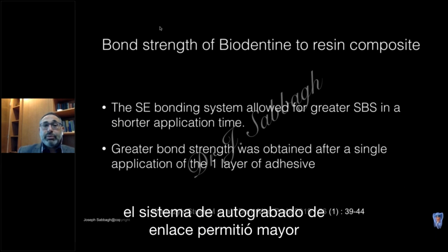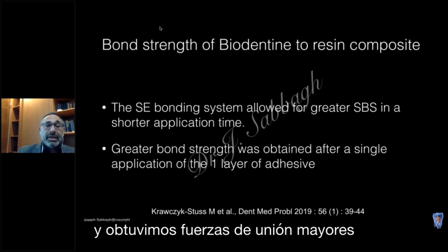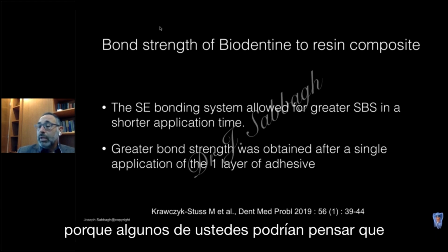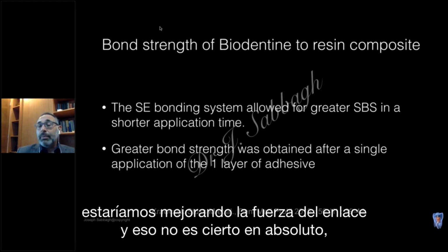The self-etch bonding system allowed for greater shear bond strength in a shorter application time, and we obtained greater bond strength when we applied one layer of adhesive, because some of you would think that if we apply two or three layers of adhesive, we are improving the bond strength, which is not true at all.